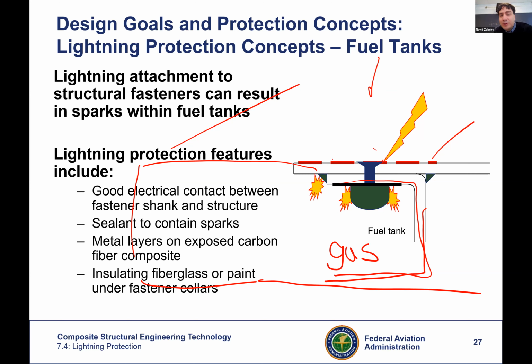First of all, you would put a layer of metallic mesh on the outer surface. And I'm going to show you a design of that. And that dissipates the energy. And there is this law, I forgot, that when the lightning strike happens, the electrons are mostly gathered on the surface. As you go through the thickness, they exponentially become less and less. But if you absorb most of the energy on the surface, it's quite good. It's not like we are leaving a lot of energy to go inside the material. So let's say we are absorbing, I don't know, 90%, whatever, of the energy.